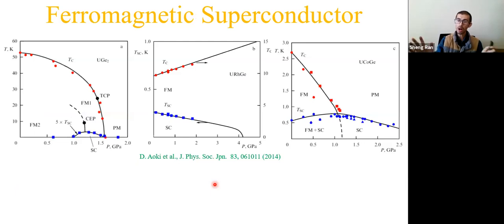And indeed, there are already such materials. There's a whole class called ferromagnetic superconductors. Here I'm showing 3 compounds: uranium germanium 2, uranium rhodium germanium, and uranium cobalt germanium. In all these 3 compounds, in some region, we have coexistence of ferromagnetism and superconductivity. In uranium rhodium germanium and uranium cobalt germanium, the superconductivity even happens at ambient pressure. In uranium germanium 2, you have to apply some pressure to suppress the ferromagnetism, then you induce superconductivity.